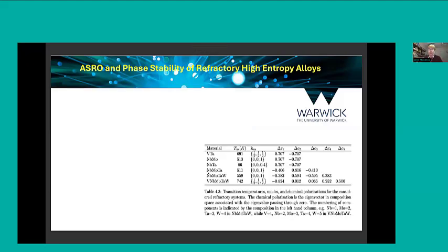Okay, so having shown the important modes and what sort of ordering is going to arise in the solid solutions, I can now just show you the results for the transition temperatures that we estimate for this ordering. Vanadium tantalum has a fairly highish temperature from which it will order, we say, into this B32 phase. Likewise, niobium molybdenum into B2 phase. Niobium tantalum has a very low temperature, showing how it wants to stay in a solid solution to quite low temperatures. And now I'm going to just mention this three component system.